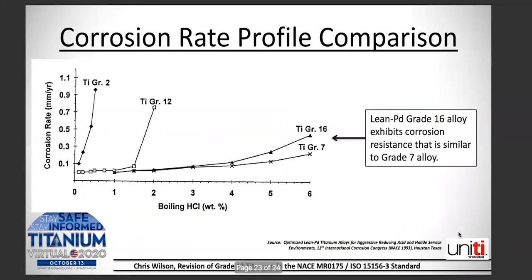So I'm going to show you that chart here. This chart is showing corrosion rate in millimeters per year of grade 2, grade 12, grade 16, and grade 7. And this is in boiling hydrochloric acid, various weight percentages. And as you can see, grade 16 is showing significant improvement over grade 12 and grade 2, and not that far off of grade 7. It's very similar. So, in many cases, I should say, grade 16 would be sufficient. So it's, again, one of those things that you should really consider looking into. If grade 16 is sufficient for your application, then the cost of that grade is significantly lower than grade 7 and should be something that you would consider.